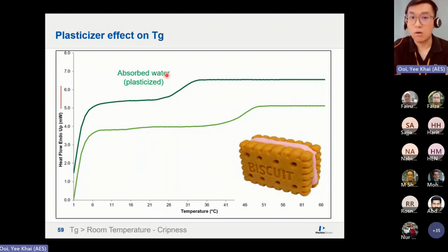But once it absorbs water or moisture from the surroundings, water by itself is a plasticizer. What does plasticizer mean? A plasticizer reduces the processing temperature or usually the crystallinity of the material. Some people use plasticizers for polymers as well, not necessarily water, but something that can disrupt the structure of the polymer to reduce the processing temperature. A lot of polymer manufacturers actually do that. So now you see the TG reduced from 40 something to 30 something because the structure is getting more and more disordered. Plasticize means the structure becomes more disordered. If you keep on storing at the same temperature, of course it becomes soggy, because it is already passing through the TG and going into the rubbery state, which is the soggy state. So this is for the analysis of the storage condition of the materials.